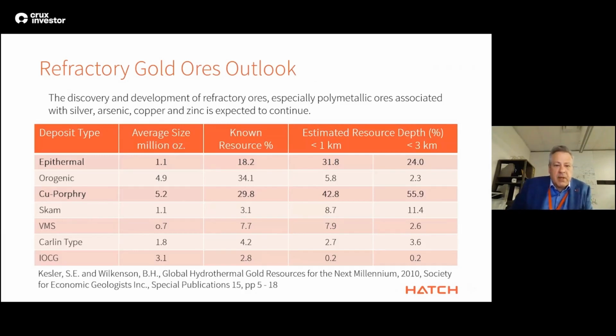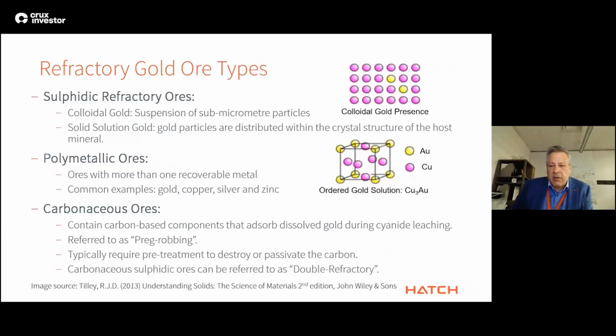As touched on previously by Chris Fleming, there are two basic sulfidic refractory ore types: colloidal gold, which consists of a suspension of sub-micrometer particles within a host mineral, as shown in the first diagram, and solid solution, in which nanometer-sized gold particles are distributed within the ordered crystal structure of the host mineral, as shown in the second diagram. Polymetallic ores are ones which contain more than one recoverable metal, such as gold, copper, silver, and zinc. Carbonaceous ores are especially difficult to treat in that they contain carbon-based minerals that adsorb dissolved gold during cyanide leaching. All of these require pretreatment to destroy or passivate the carbon and are sometimes referred to as double refractory.